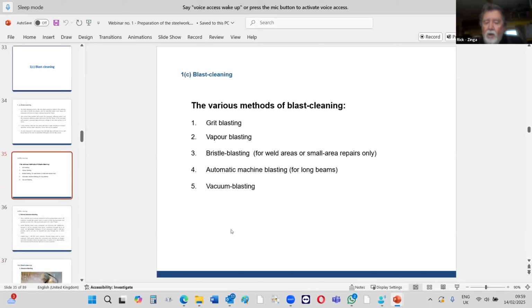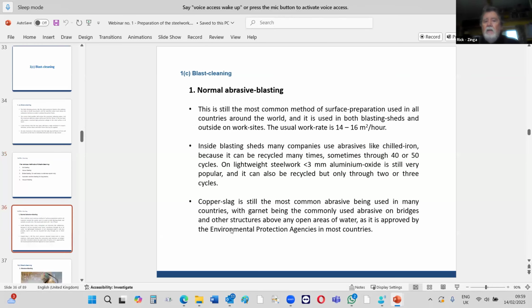So you have different types of blasting. Obviously, the oldest is grit blasting, which is with a dry grit. So this is normal abrasive blasting. You can prepare the steel at 14 to 16 square meters an hour. Inside steel sheds where they recycle the abrasives, then we recommend to use chilled iron.